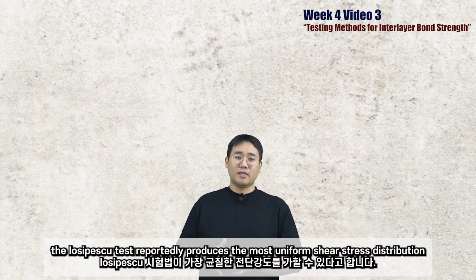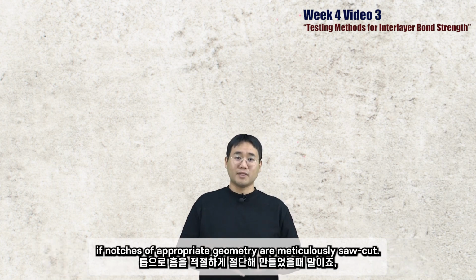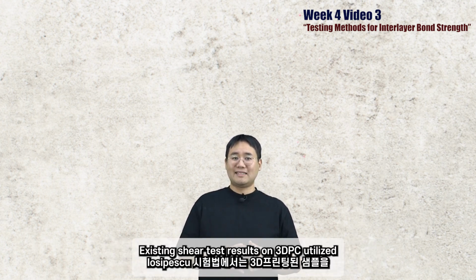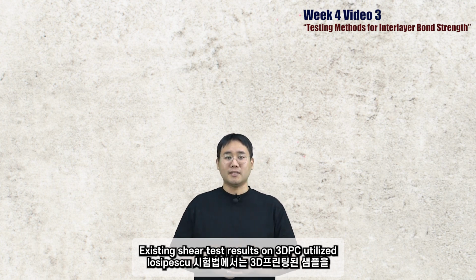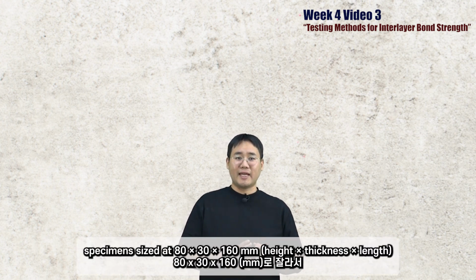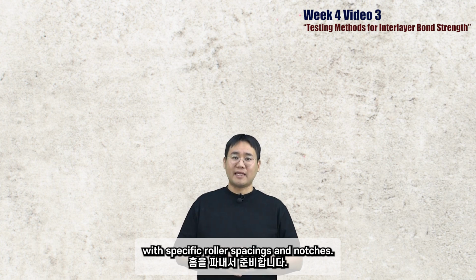Among these, the Iosipescu test reportedly produces the most uniform shear stress distribution if appropriate geometry is used or the specimen is meticulously saw cut. Existing shear test results on 3D printed concrete elements utilize specimens sized 80 by 30 by 160 millimeters, which are the height, thickness, and length, with specific roller spacing and notches.